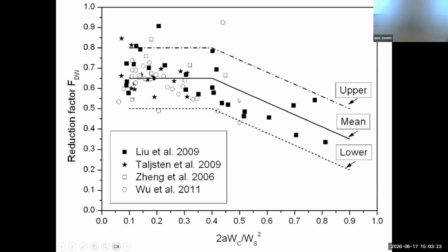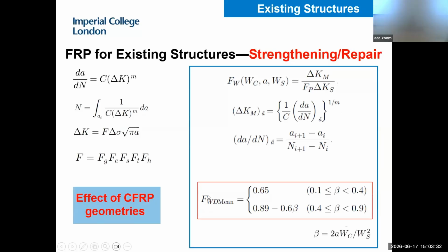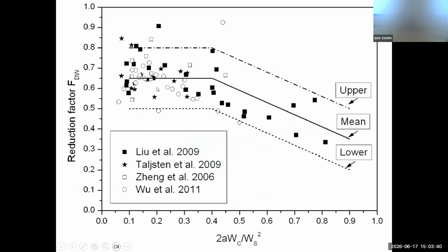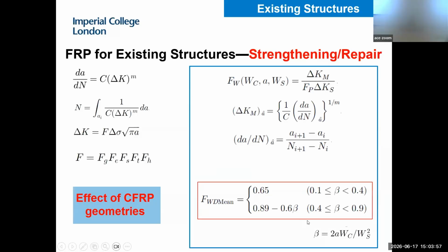So we calculate a lot of data points using experimental curves, then we do curve fitting. This is the result of curve fitting, a two-segment function. As you can see, the modification factor here is determined by the experimental results. If you do a lot of fatigue testing, you can get a more accurate result, meaning this formula will evolve and become more accurate as we have more experimental data in the future.